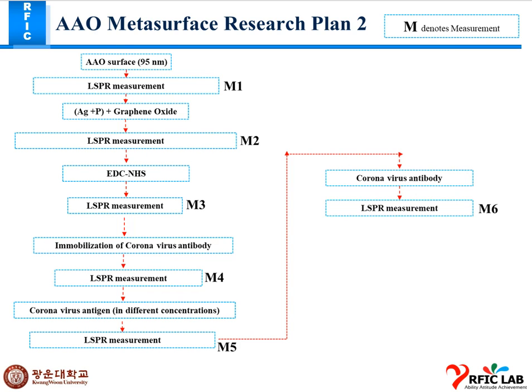And the second plan is quite different from the first plan, because here we didn't wash the surface. We simply do the AAO nano surface LSPR measurement, then put the complex structure on and do the LSPR measurement, then put the EDC, then LSPR measurement, and then antibody immobilization, then again LSPR measurement. We use different concentrations that I already told you: 1 microgram per ml, 5 microgram per ml, and 10 microgram per ml. These three different concentrations we use here on the surface.